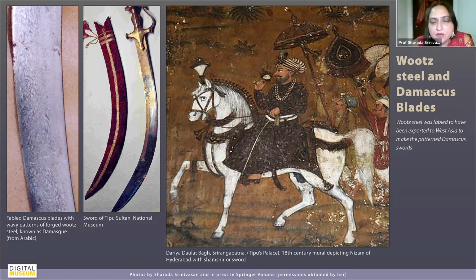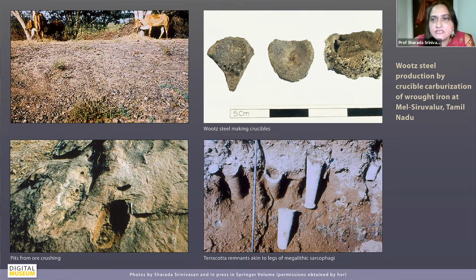And in fact, it is really from Golconda that you see a lot of accounts from the 16th century by Tavernier and others of the making of these cakes of wootz steel. But what is interesting is that it is a longstanding tradition in South India. And as I said, the roots go back to the Iron Age, early historic period. This is one of the sites that I identified, Mel-Siruvalur, near Thiruvannamalai, just to explain the process. And you see these fragments of crucibles which are used for making steel. If you put them all together, it gives you the shape of that cake